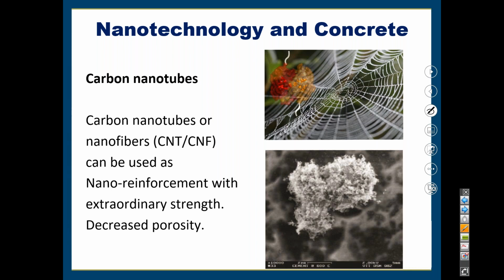Another thing that has evolved is the use of carbon nanotubes. So nanotubes are kind of a form of biomimicry where they looked at spider webs and how strong the silk that is used is, very, very strong. And they try to imitate that by creating these nanotubes that are either embedded within polyvinyl alcohol fibers, PVA fibers, or used on their own as a carbon nanofiber and mixed into the concrete to help control the propagation of cracks on a nanoscale, on a very, very small scale, which overall contributes to the overall strength of the concrete.